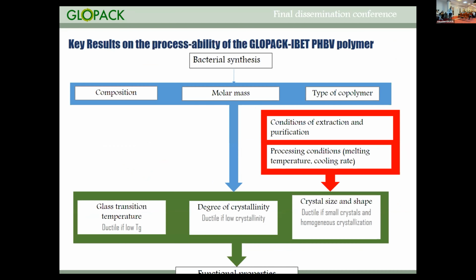So to conclude on these studies, the functional properties of polymers, and especially PHBV polymers, are governed by three main parameters: the glass transition temperature, the degree of crystallinity, and the crystal size and shape. If you want to target flexible materials, you will try to have a glass transition temperature as low as possible. You will try to have a very low crystallinity, and you will target very small crystals. And overall, what is also important is the homogeneity of this crystallization.